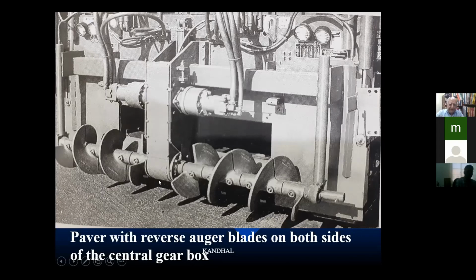The paver which they had was some model which did not have the reverse auger. So that's why there was a lack of density here. There was insufficient material below the gearbox, lack of density. Water was being pulled in there, and it created stripping, and the mix collapsed there and developed cracking on the top.